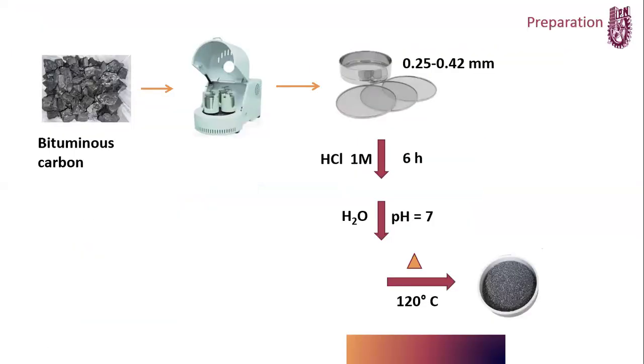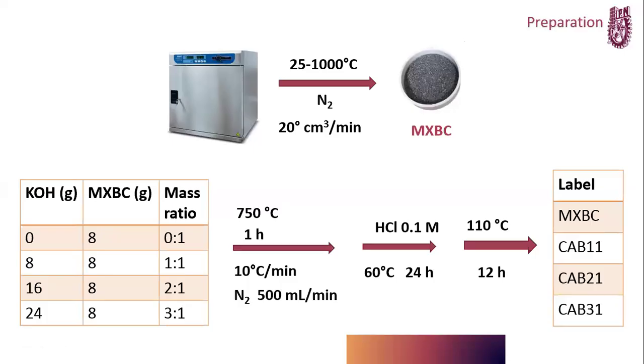For the preparation of activated carbons, the bituminous carbon was ground using a planetary ball mill. The carbon product was sifted to diameters between 0.25 and 0.42 millimeters. The carbon was treated with a solution of hydrochloric acid for 6 hours at room temperature with stirring. Subsequently, it was washed with deionized water until a pH of 7. After that, the material was dried at 120 degrees. Thermal treatment conditions for eliminating impurities and activating the raw material were established within a thermal range from 25 to 1000 degrees in nitrogen atmosphere with a flow rate of 20 cubic centimeters per minute.